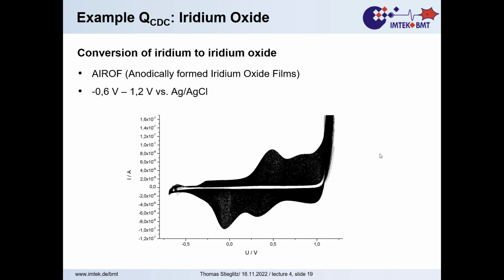It's not the salt, it's the water, the OH and the H that reacts with the iridium, and the smooth metal gets into that iridium oxide structure, and more iridium oxide is growing. If you now imagine iridium versus iridium oxide, there's the oxygen part that has to be placed somewhere in the lattice structure of the iridium. And that means it gets more spongy. Well, it's not a sponge, but it gets larger. And in the worst case, it flakes off.